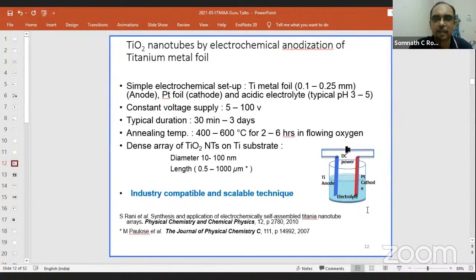You have to treat it thermally. You have to give a heat treatment after this process is over, in an oxygen flow. Of course, normal air has a lot of oxygen too, so it works. Then we can get nanotubes with diameter 10 to 100 nanometers, and in principle the entire thickness of the titanium foil can be anodized. In fact, there are papers that have shown that if you run the anodization process very delicately and under strict observation, the entire thickness of the metal foil can be made into the nanotubular structure. So it all depends on what we want.